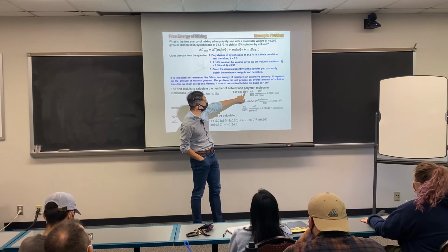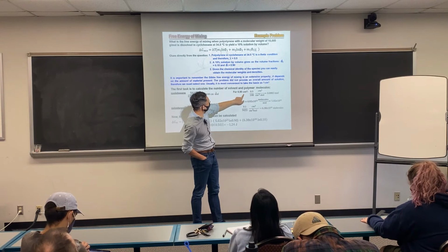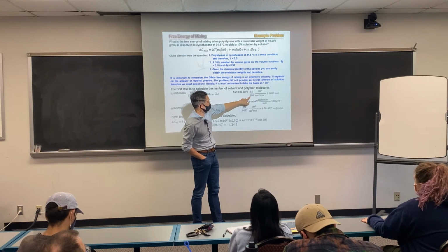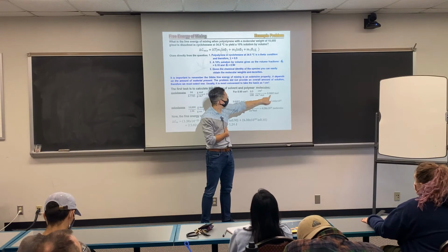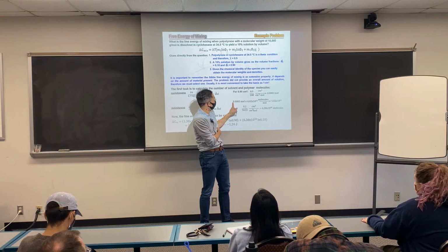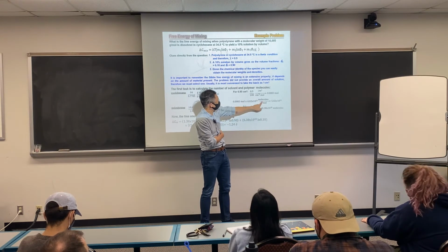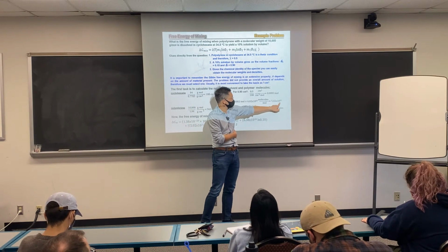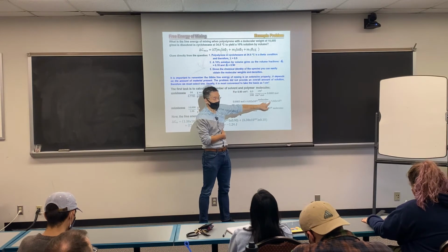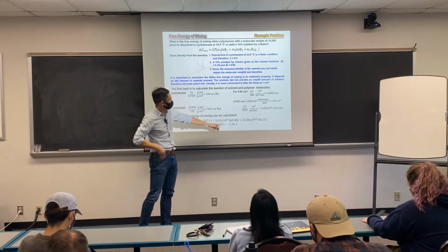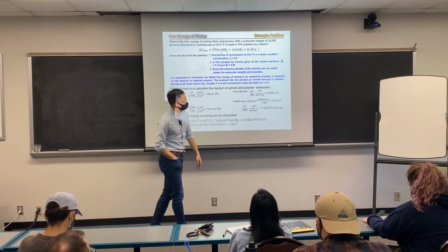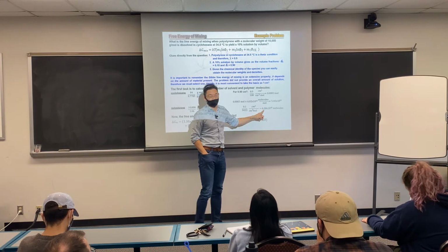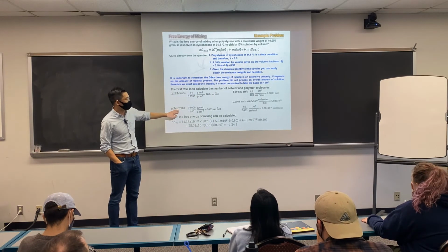Okay, this is shown here. We assume 1 cubic centimeter, so among that there will be 0.9 cubic centimeter of solvent, divided by the volume per mole of solvent. You can get how many moles of the solvent cyclohexane, multiplied by the Avogadro number, and this will give you N1. Okay, and you can apply the same approach to the polymer to get N2. It's not too surprising that your polymer number is much smaller, just because each polymer chain is pretty long, and you only have 10% of polystyrene.